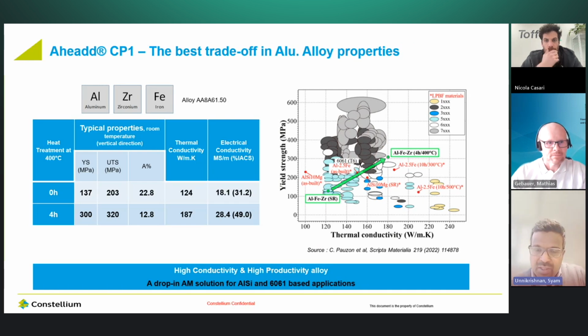So this particular image is really interesting. You can see yield strength on the y-axis and thermal conductivity on the x-axis for most of the aluminum alloy systems. If you look at where CP1 is placed, this is the best trade-off that you can see, where you can have a reasonably good yield strength and very good thermal conductivity. No other alloy is positioned in this kind of situation, and we can still fine-tune the properties by adjusting the heat treatment. So CP1 will be able to address, I would say, 80% of the aluminum applications that we can see in the additive manufacturing world.